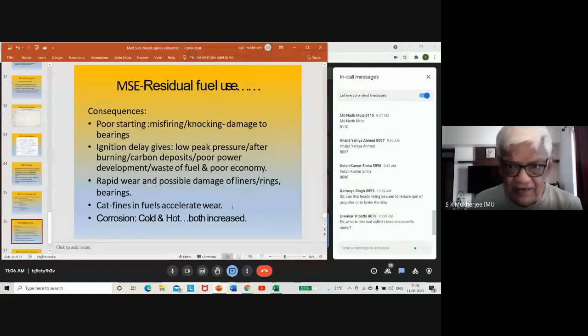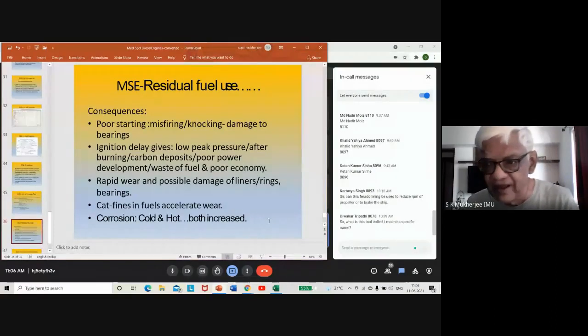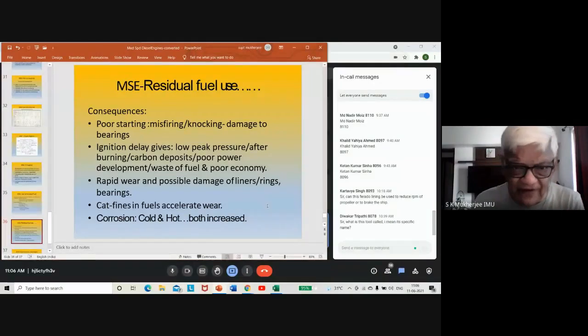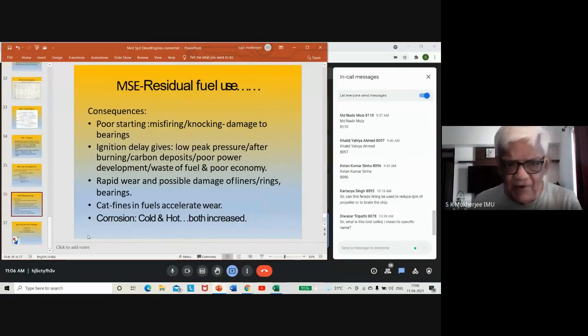Rapid wear and possible damage of liners and rings and bearings. Catalytic fines in fuels accelerate wear. That is true. Catalytic fines are mainly silicon oxide and aluminum oxide, if you remember. Corrosion can be cold corrosion as well as hot corrosion. Both are increased because the residual fuel also contains some amount of sulfur. But of course, now with low sulfur fuels being utilized, the amount of cold corrosion has diminished.